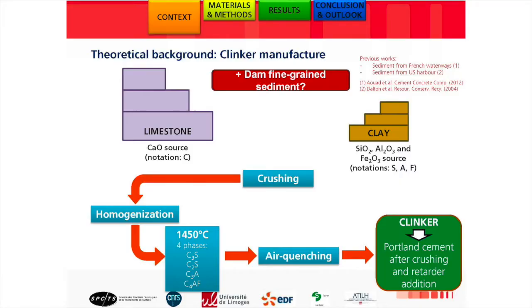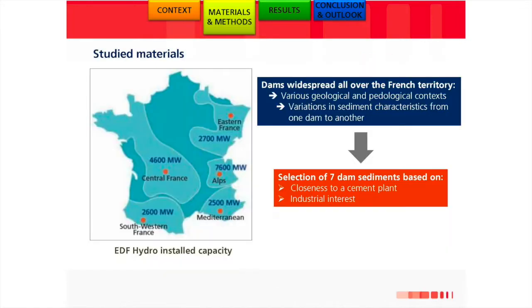These are air quenched, and after the clinker is crushed, we obtain the cement, which is mixed with different additives to get the proper setting characteristics. So the idea is, would it be possible to replace part of the clay or limestone by these sediments? Because, as you can imagine, these sediments are rich in all the oxides found in the clinker.